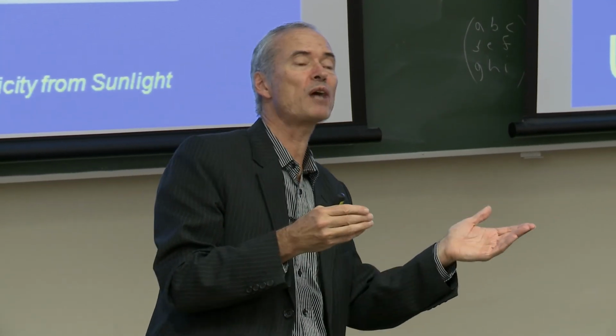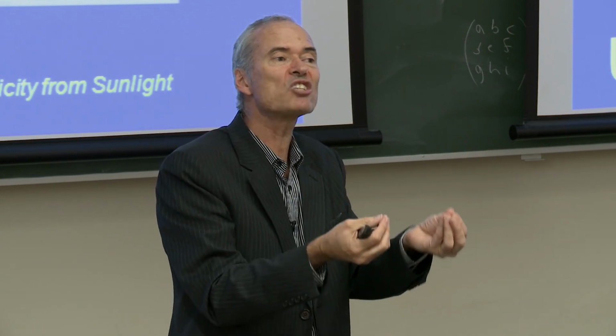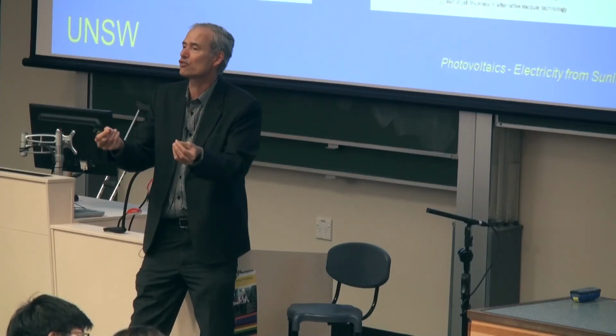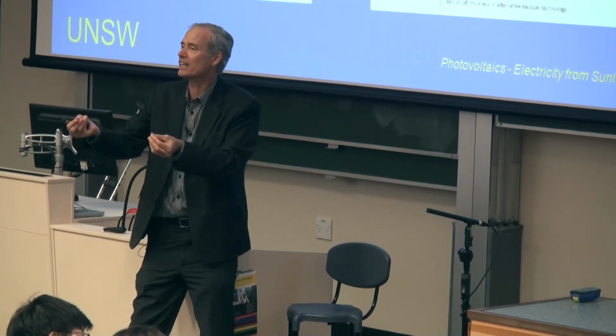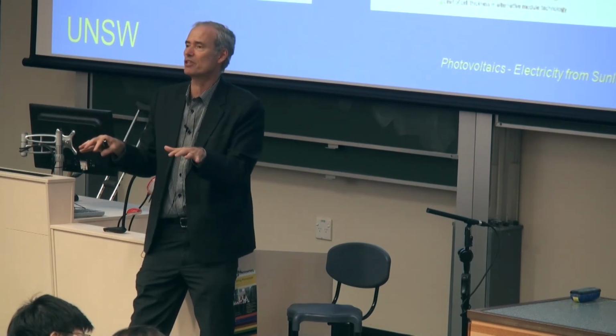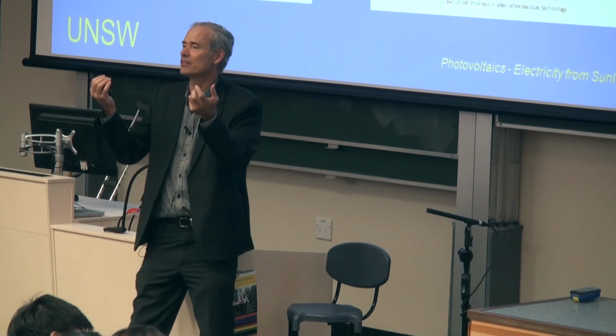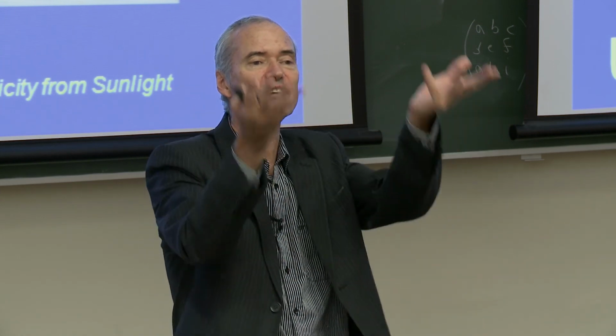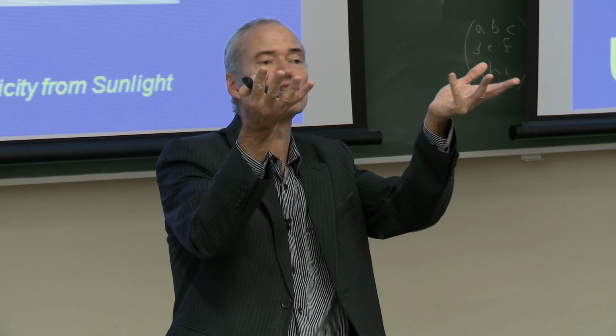So they've gone to a different approach, because what they've realised is that during a normal multicrystalline silicon ingot growth, you are still generating this stress within the silicon, but the stress relieves itself because you've got grain boundaries all over the place. And so if you get any defects forming, the defects simply propagate to the nearest grain boundary and extinguish themselves. So they don't propagate through the ingot. Provided you've got grain boundaries close enough, you can form an entire ingot, and when you get to the top of the ingot, you don't have any higher dislocation density than when you started.